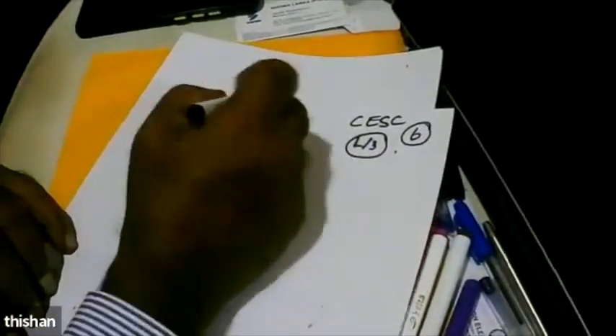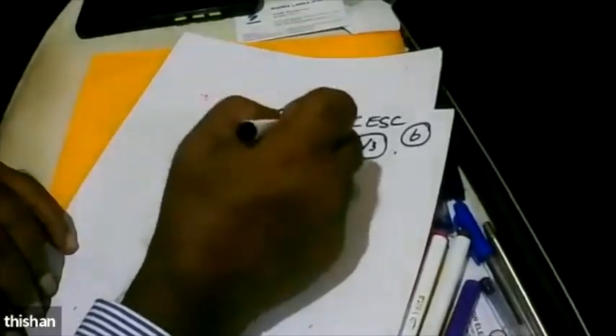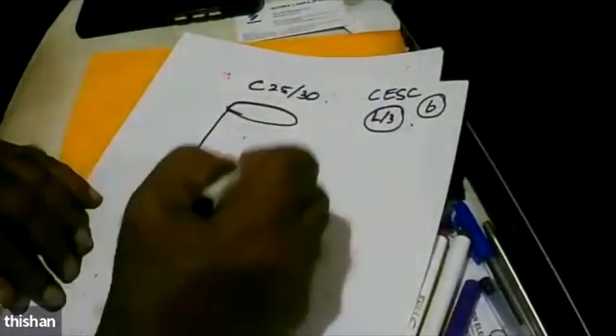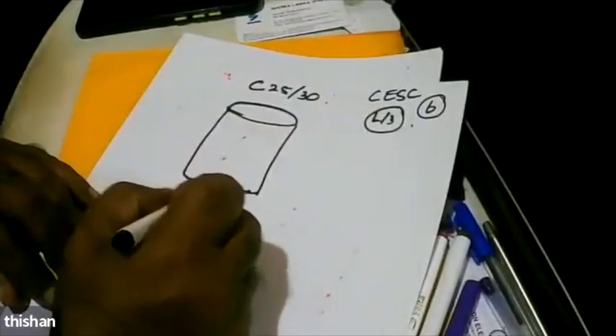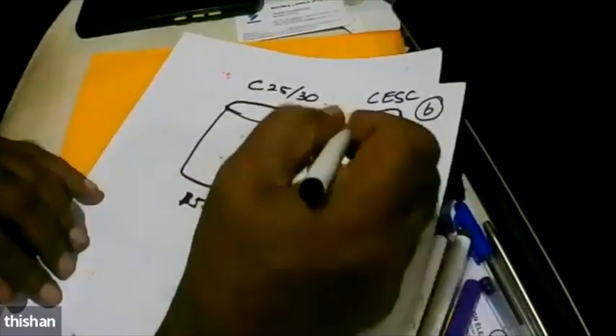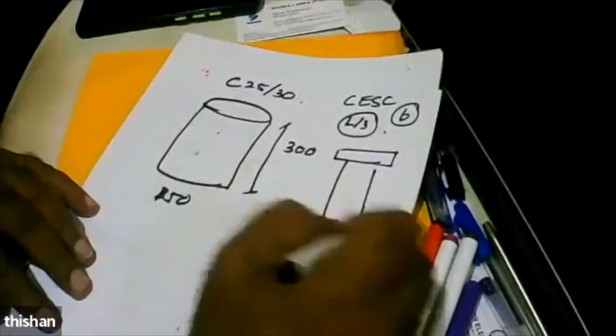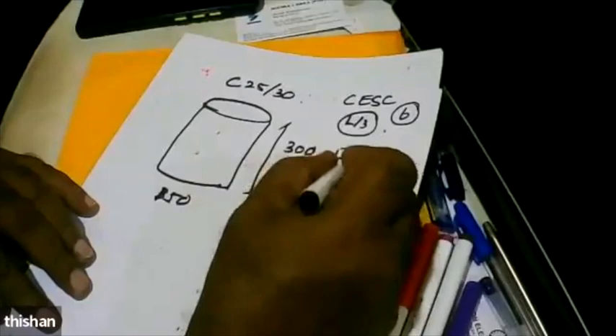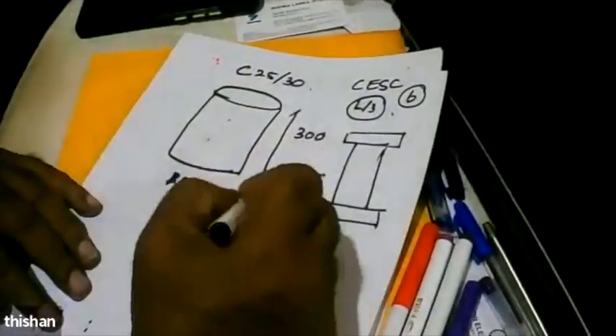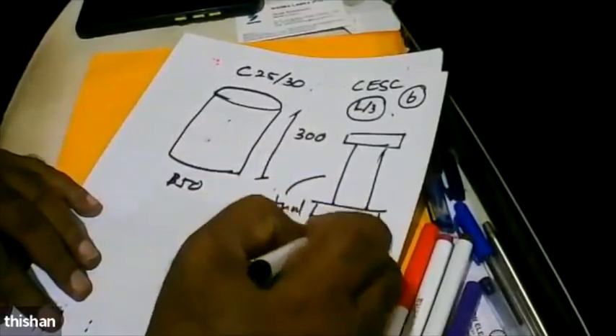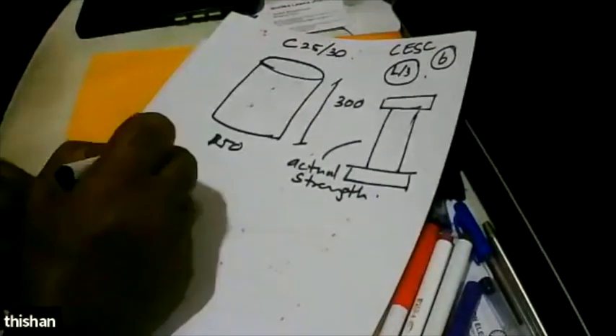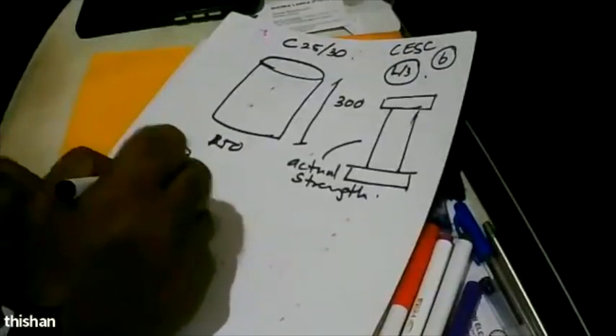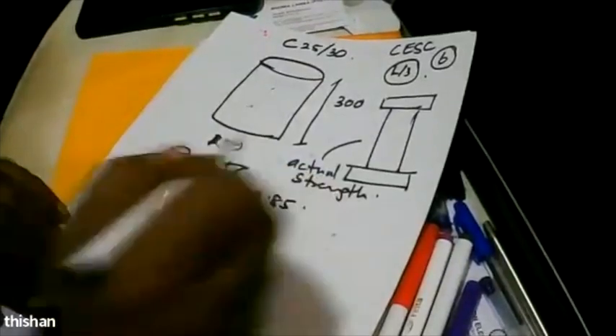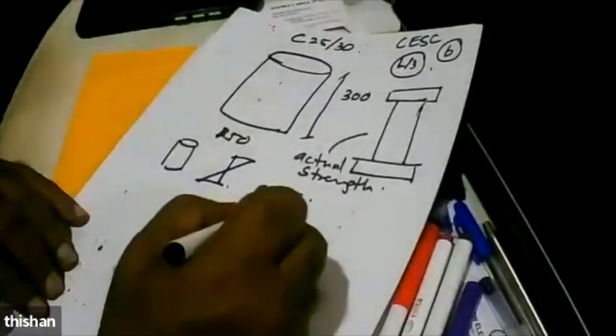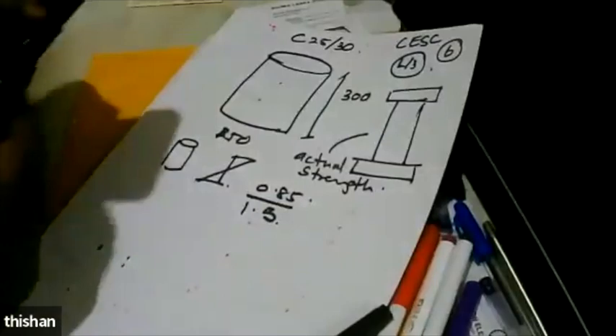Okay. Right. So now Eurocode. C25/30. So earlier we were talking about 30 megapascal concrete. Now we are using cylinders, 150 millimeter circular, 300 millimeter height, and we place it under the platens. So here there is no confinement, so what you get as strength is actual strength. Then we have to say, now we test this way, so we need 0.85. And then we need a 1.5 partial factor of safety. Right? Partial factor of safety.